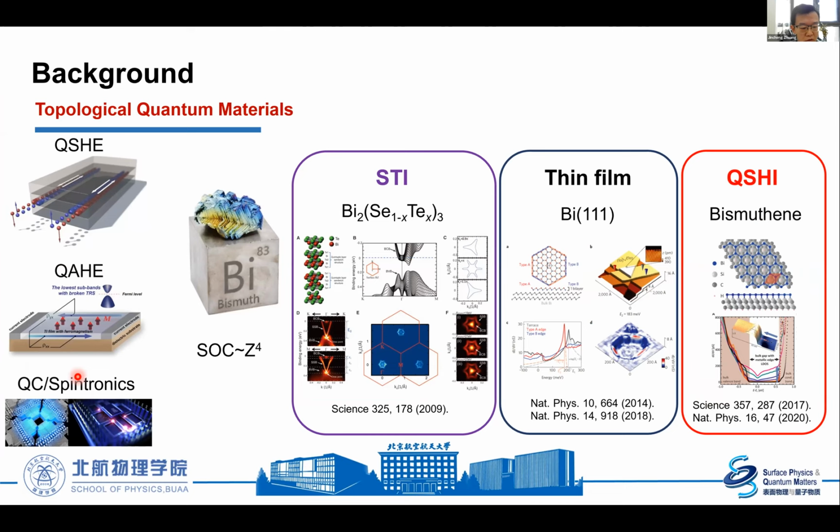And from the view of band theory, the spin-orbit coupling strength is crucial for the band inversion. And the spin-orbit coupling strength is proportional to the fourth power of the atomic number. So it is possible to explore topological quantum materials in materials with heavy elements. For example, bismuth, which is the heaviest element among the non-toxic and non-radioactive elements. And in experiment, the first three-dimensional strong topological insulators have been realized in bismuth-based Bi2Se3 or Bi2Te3 with